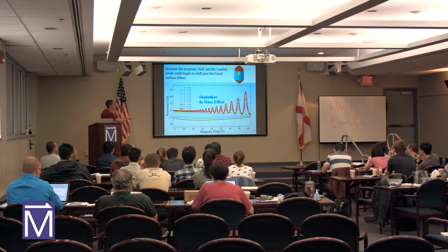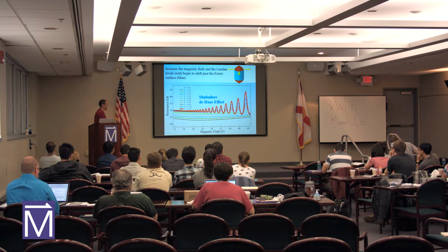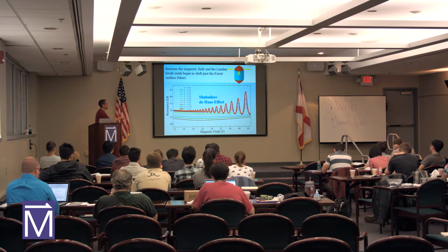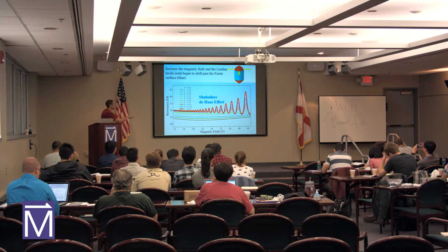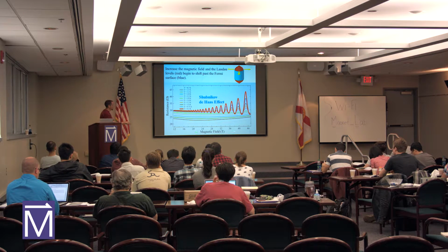Okay, the resistance of the sample shifts up and down as we see the quantum oscillations. We can also see some of the things that we already talked about, that as we get to the lowest temperature, half a Kelvin, certainly the data is the most obvious. And as the temperature increases, the oscillations fade away and we can barely see them. And also that the spacing increases between the oscillations as we move out in magnetic field, because it's not uniform in magnetic field strength. The spacing is uniform in inverse magnetic field.